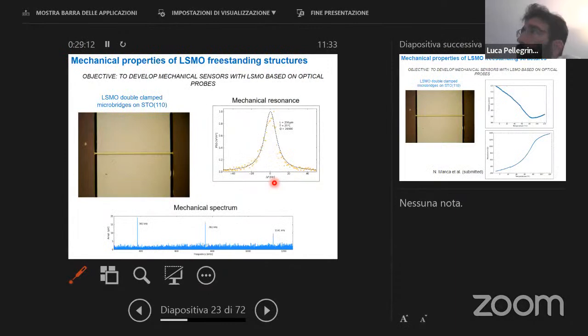Now let's move to another topic we are working on right now. This is a freestanding manganite bridge, which is very long, as you can see here, 200 microns. The yellow part is freestanding, a very nice structure, and this double-clamped micro bridge was made on 110 STO. This is the mechanical resonance, the mechanical spectrum. You see the first mode, second mode, and the other modes here, and this is the resonance of this structure, which has quite a large Q factor.